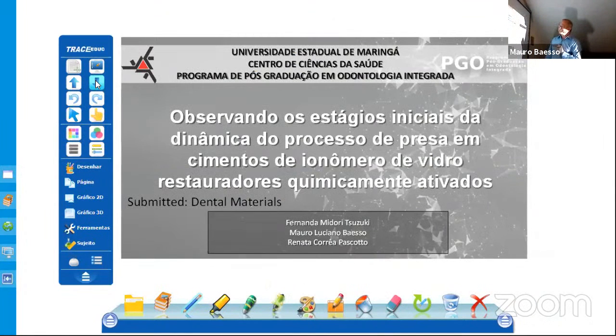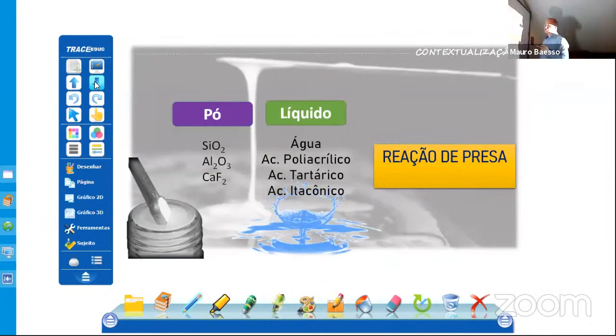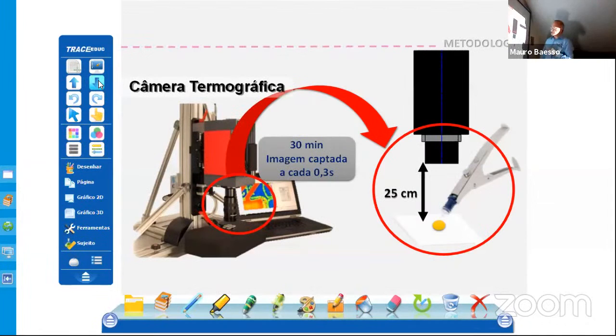And the last one is not a photothermal technique. We use a thermographic camera. Sometimes it's important to get the temperature of the tissue, and we evaluate how it changes when we prepare the cement during the preparation for tooth restoration. This is a very important process, because the time necessary for the cement to set is very important for the chemical bond that you make between the cement and the tooth, the link between those. And we use a thermographic camera.